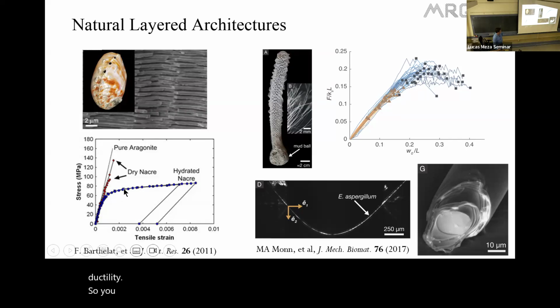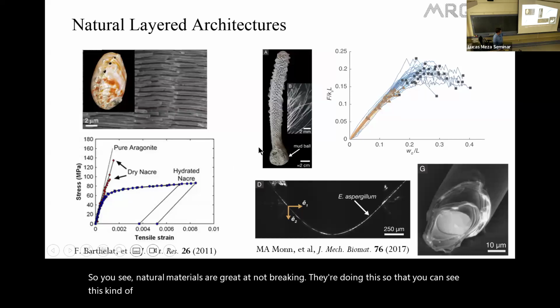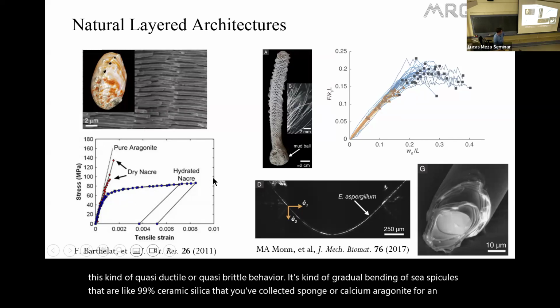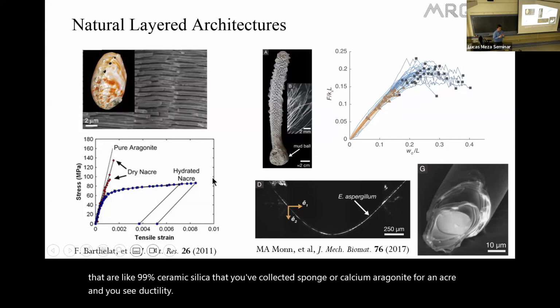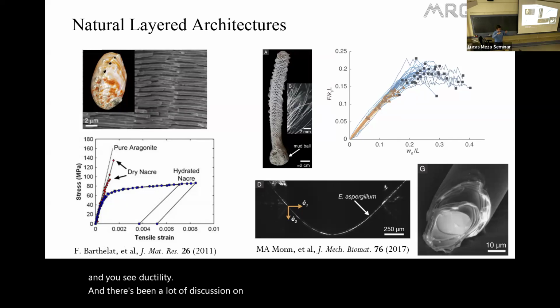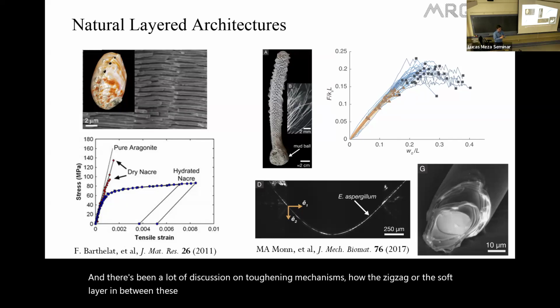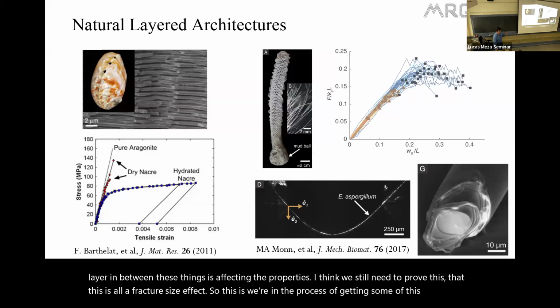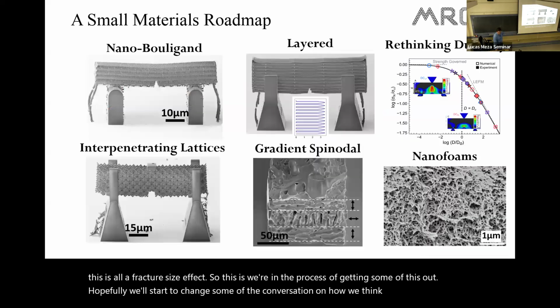So you see natural materials are great at not breaking. They're doing this so that you can see this kind of quasi-ductile or quasi-brittle behavior, kind of gradual bending. Take these sea spicules that are like 99% ceramic silica for the Euplectella sponge or calcium aragonite for nacre, and you see ductility. There's been a lot of discussion on toughening mechanisms, how the zigzag or the soft layer in between these things is affecting the properties. I think we still need to prove that this is all a fracture size effect. So we're in the process of getting some of this out. Hopefully we'll start to change some of the conversation around how we think about material ductility.